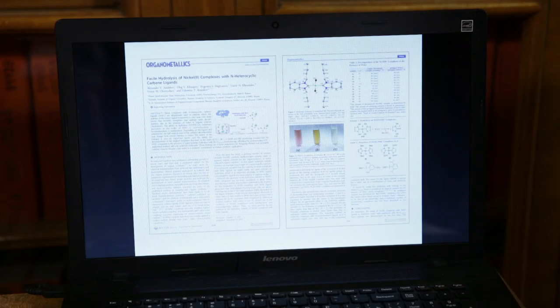Our recent study in Organometallics is dealing with the carbene complexes of nickel, these NHC carbenes, very well-known ligands, and usually we believe that the strength of the interaction between metal and ligand is enough to stabilize the complex as a homogeneous catalyst. But we have surprisingly found that these complexes can undergo hydrolysis by reaction with water, and they also can decompose to form nickel clusters and nickel particles and the free ligand. So the question is also important for NHC complexes, at least for nickel. Concerning our studies, which have been published in Organometallics, I think these are the three most interesting ones. Great, I agree. I think it's beautiful chemistry.